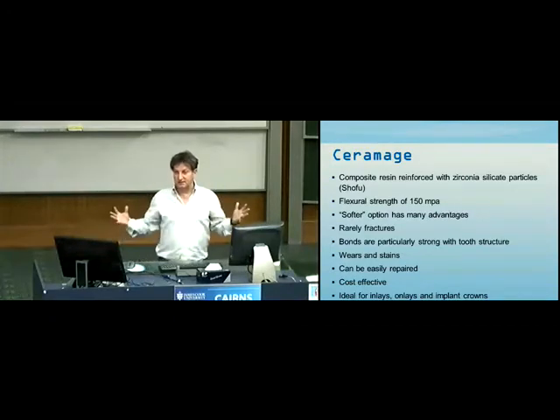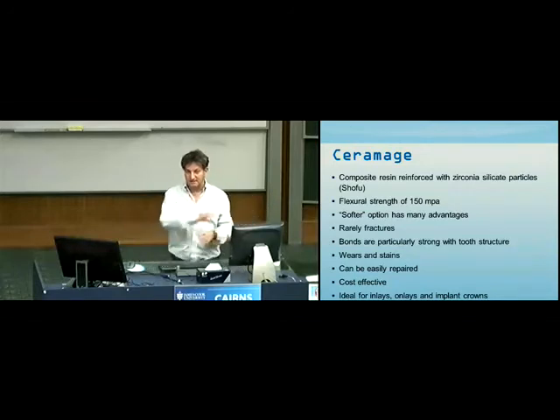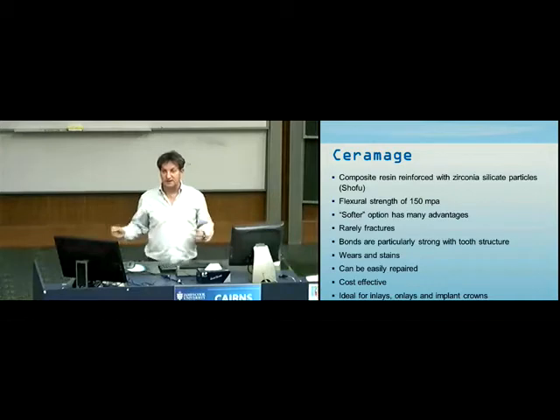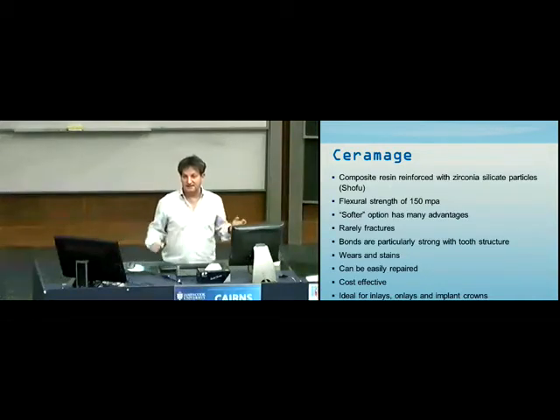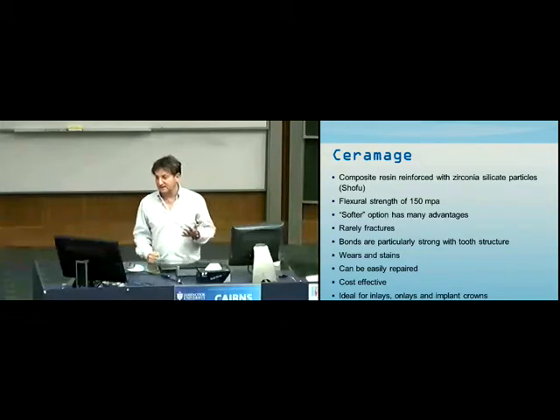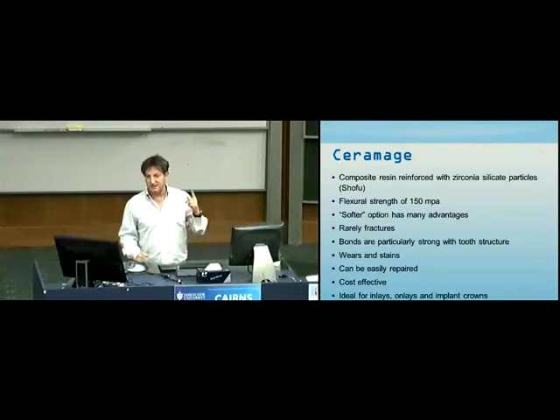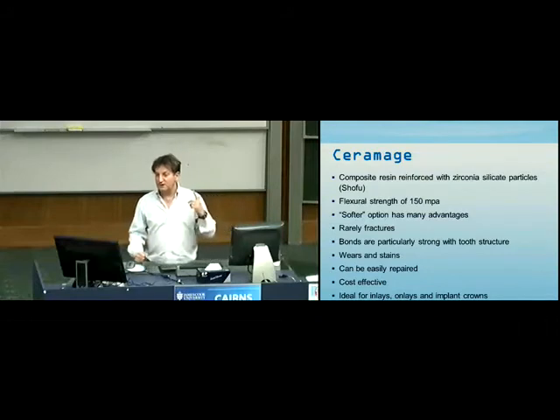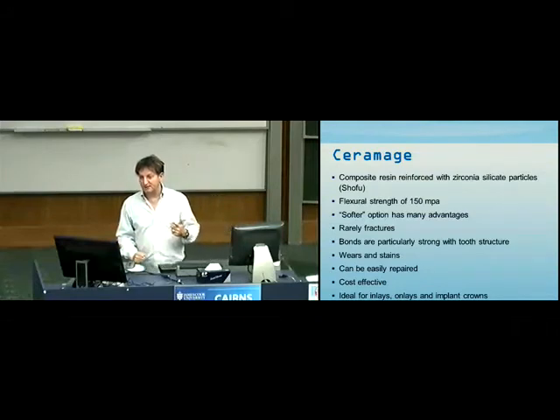In those days, we were putting amalgams everywhere, and amalgams, of course, were a trench through the middle of the teeth, and you've got cusps and cracks everywhere. So what would happen is this very hard material on your VMK would be belting against a tooth which already had some cracks in it, and bingo, off came a cusp. And then we were putting pin amalgams and pin composites and doing all sorts of stuff back in those days. It all worked well, but we weren't really aware of what was actually happening.